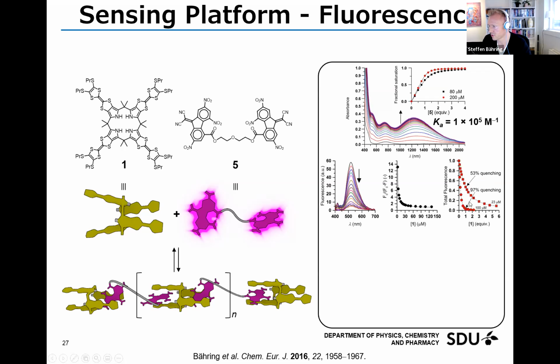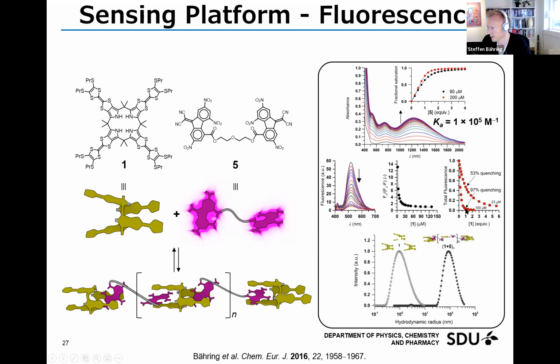If we increase the concentration a bit, then we would favor more supramolecular polymerization. And this shows that at 100 micromolar total concentration, we have 97% quenching. So this system at 100 micromolar might be able to show indicator displacement behavior. We also had DLS to show that we have a significant change in the hydrodynamic radius when we have the bisfluorenone present as well.